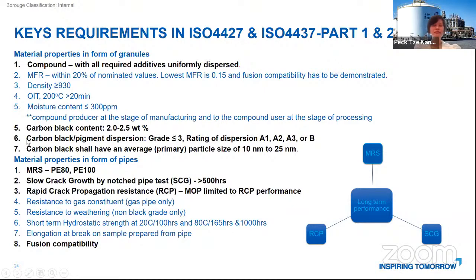When it comes to the carbon black dispersion requirement, it is also quite a detailed stipulation. Carbon black content needs to be between 2 to 2.5 weight%. Pigment dispersion has to be rated according to the standards as not more than grade 3, and a dispersion rating of not more than B. The carbon black also has to have a certain size, not too big, because if you have too big a particle size, you're not having very good UV resistance. So 10 nanometer to 25 nanometer will do the job.